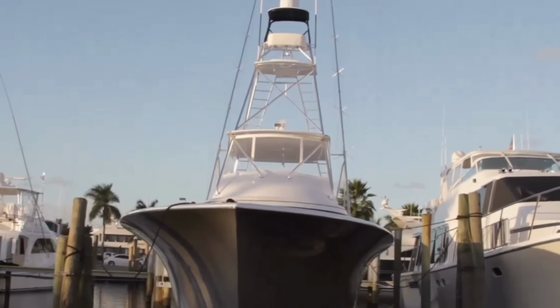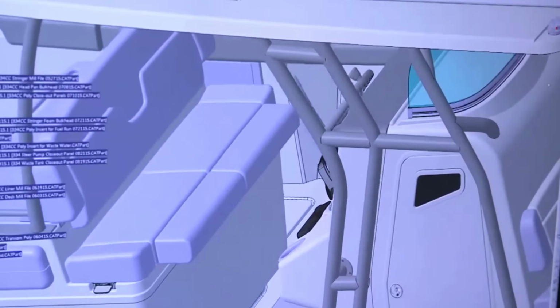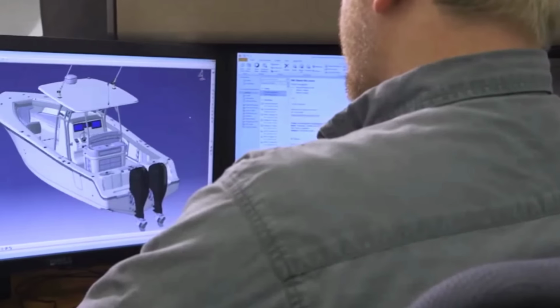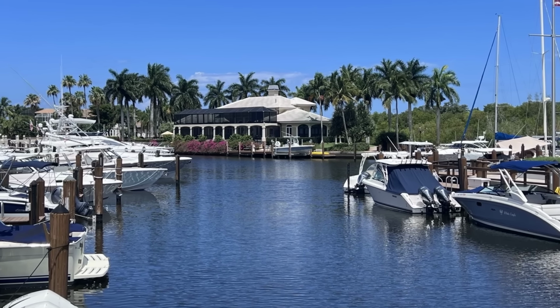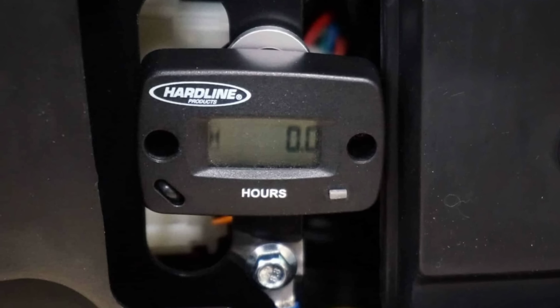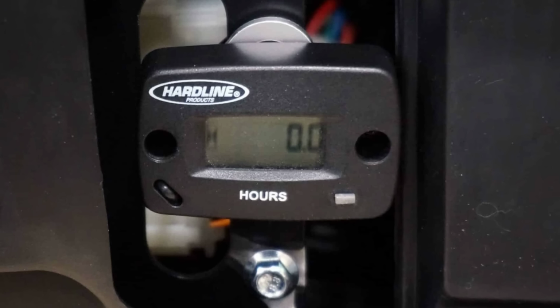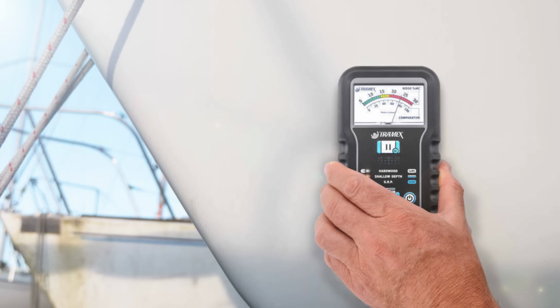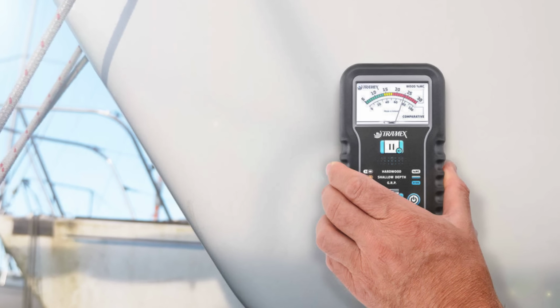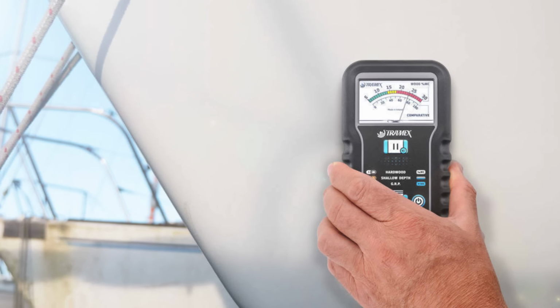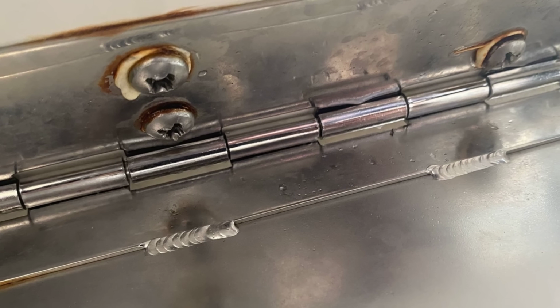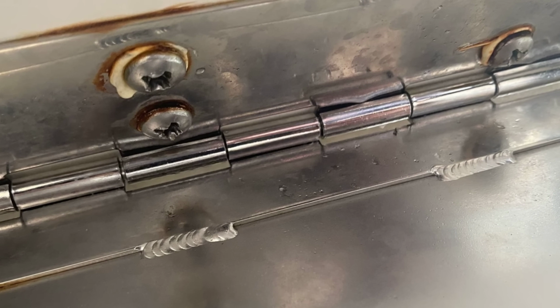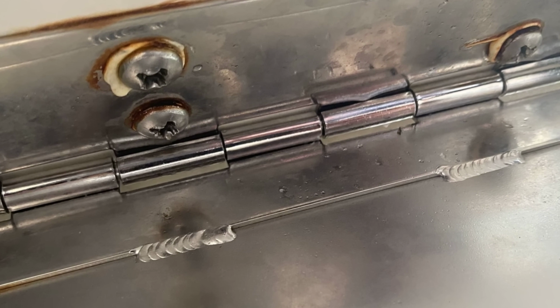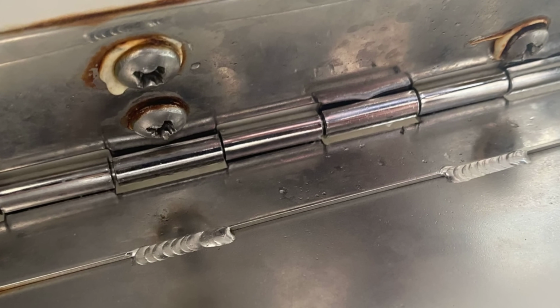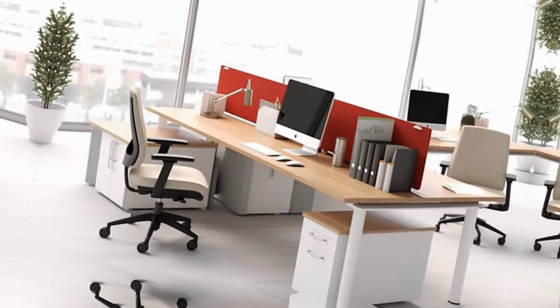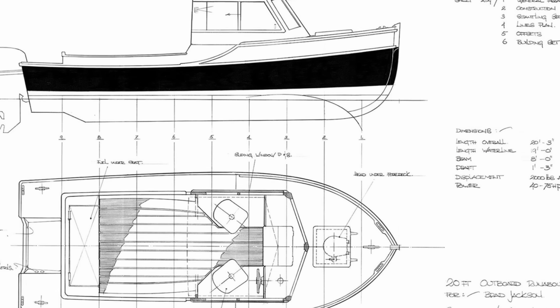Most boats do not die from hard use. They die from how they were built. A boat sitting in a saltwater slip right now with 200 hours on the engines and a clean gel coat can already have a transom absorbing water, a stringer system beginning to delaminate, and hardware quietly introducing galvanic corrosion into the hull from the inside out. Nobody disclosed that at the point of sale. Nobody put it on the spec sheet.